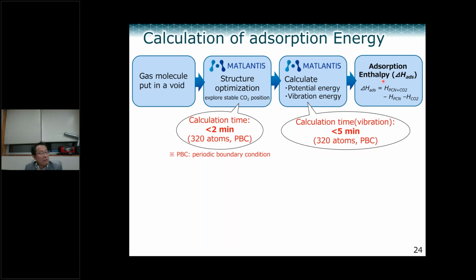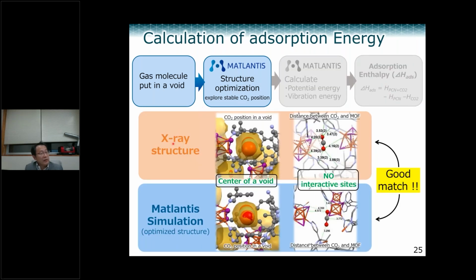Okay, let me show you the result. First, the comparison between the X-ray structure and the Matlantis simulation. This is the X-ray structure and this is the Matlantis structure. From a distance, you can tell how close they are to each other. First of all, the position of CO₂ is exactly the center of this void. Matlantis also expected that. And from a distance, Matlantis very nicely reproduced this structure. Eventually we got a very good agreement between the X-ray and Matlantis.